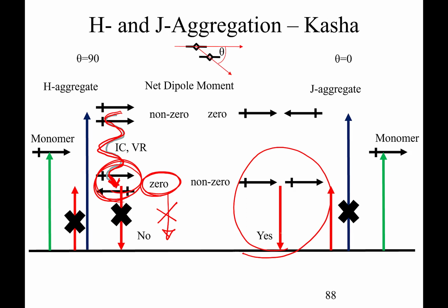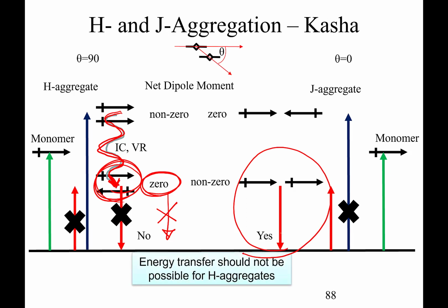So it turns out that because this fluorescence should be zero for these H aggregates, we should not see any fluorescence at all, so we think that energy transfer shouldn't be possible. And that's why we're scratching our heads here, because we've observed that there is energy transfer for these materials.